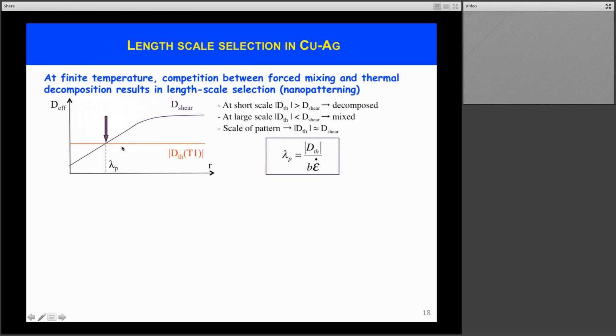So the important point is that now, if we were to go back to the situation where there's a competition between the mixing forced by plastic deformation and phase separation promoted by thermodynamic forces, which is this diagram here on the left side, the effective diffusion coefficient induced by shear increases with the pair separation distance r, whereas thermal diffusion in red here is independent of this pair separation distance. And so you can see that the outcome of this competition becomes scale dependent. In this particular case, at short scale, thermal diffusion is more effective than the forced mixing, and so we expect the system to be decomposed. At larger scale, however, the mixing forced by plastic deformation is more effective, and so we expect the material to be homogeneous at that scale.